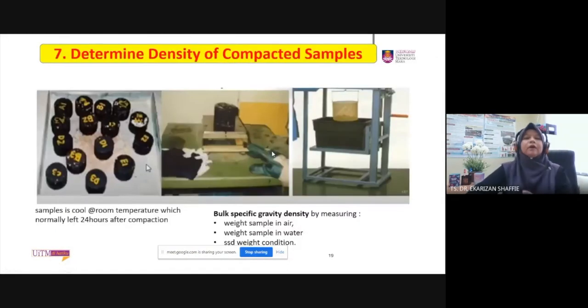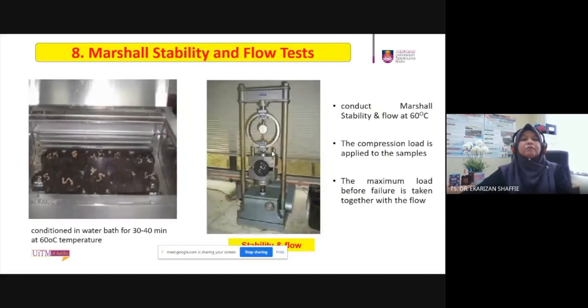For the next step, we have to determine the density of the compacted sample. After preparing the sample from the previous step, it is cooled at room temperature, normally left for 24 hours after compaction. Then we conduct the bulk specific gravity and density test by measuring weight in air, weight in water, and saturated surface dry weight. For the next step, Marshall stability and flow test, we need to condition the sample in a water bath for 30 to 40 minutes at 60 degrees. Then we conduct the stability and flow test using this machine. The compression load is applied to the sample, then we collect the data from the maximum load before failure, taken together with the flow. From this machine, we get the stability and flow test results.